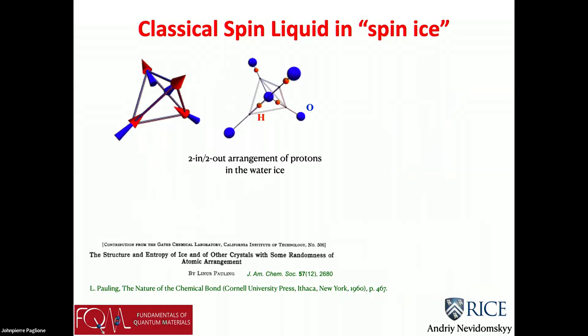If you look at the water molecule, it turns out that the particular oxygen atom, which is blue over here, is on average surrounded by 4 hydrogens. And it turns out that the best way to optimize this is to have 2 of the hydrogen atoms closer to the central oxygen and 2 of them farther. Of course, you have to do it not just on one tetrahedron, but on all the tetrahedra. And the structure of water ice could be mimicked by what I just showed you. You assign an arrow pointing in if this hydrogen atom is closer to the central oxygen, like here, and pointing out if this hydrogen, the red atom, is farther away from the center. So for now, this is just an analogy, a tool telling you that you could assign arrows in a fashion pointing.